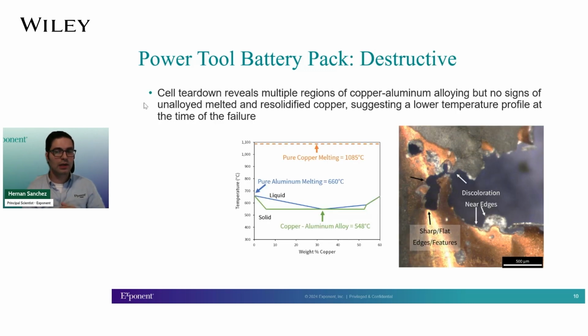And in this case, we were able to look at the unfolded cell, and it turns out that we were seeing a lot of missing copper current collector, but all of the edges of that actually had this silvery discoloration. And this is where, once again, being able to use SEM EDS was very powerful, because we were able to determine that these were all signs of copper aluminum alloying. And for those of you that have dealt with alloying and understand phase diagrams, the temperatures at which you can melt a copper aluminum alloy are much lower than for melting pure copper.